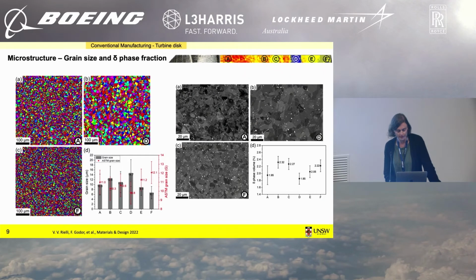So what we did here is we characterized a bunch of interesting regions. I mainly want you to focus on this region D here, which is the one with the kind of worst case properties. So what we can see on the micrometer scale here on the left, you can see individual crystallites, so individual grains. That's how this material is made up on the micrometer scale. And we can see that in this region D, the grain size is much larger.